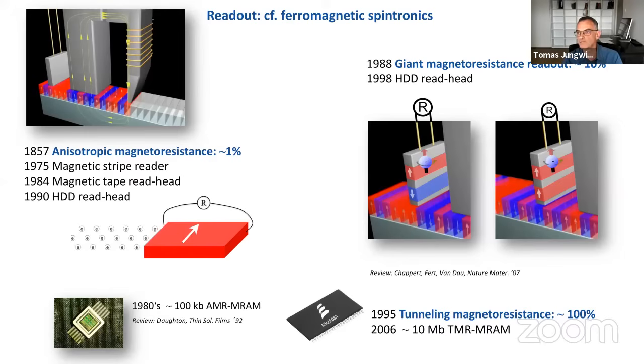But we all know that the real breakthrough in spintronics was due to the discovery of giant or tunneling magnetoresistance effects. The relative resistance changes are 1 or 2 orders of magnitude larger than in anisotropic magnetoresistance. And instead of using a simple magnetic film device, these devices comprise at least two magnetic parts. One is the reference, which is a fixed magnet, and then we have the recording element, and depending on the relative orientation between the reference and recording magnet, we have either low or high resistance.